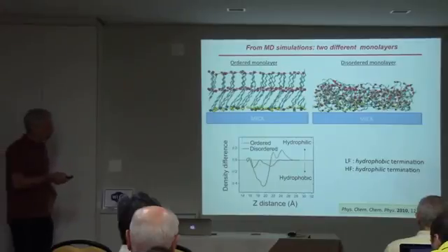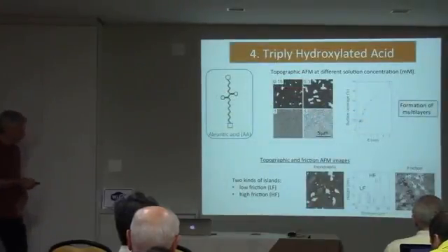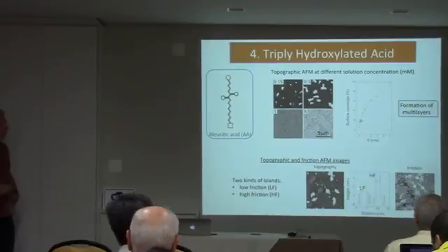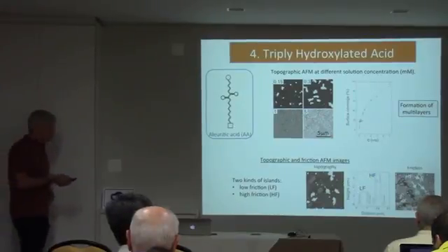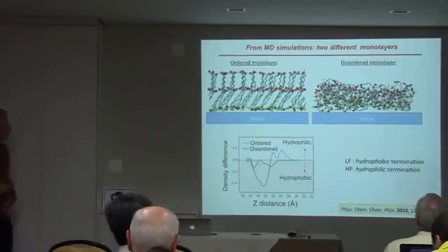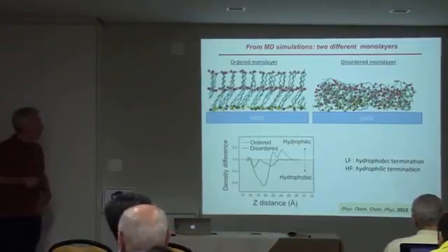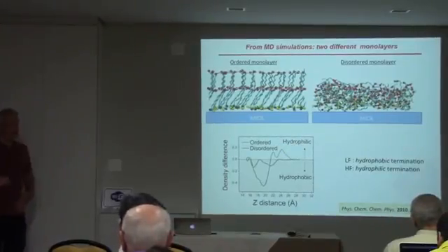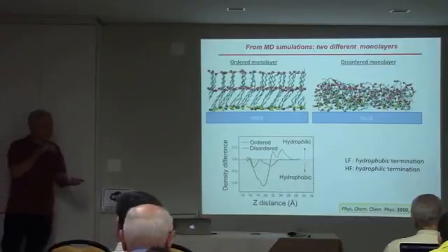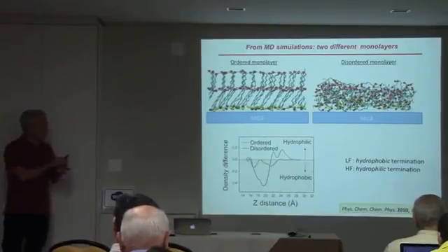This can be correlated with the two regions. The low friction corresponds to the hydrophobic structure, and the high friction to the hydrophilic. This is because of the interaction of the tip with the system.